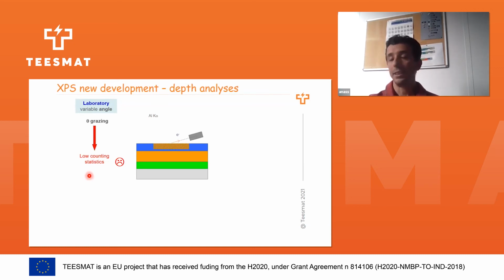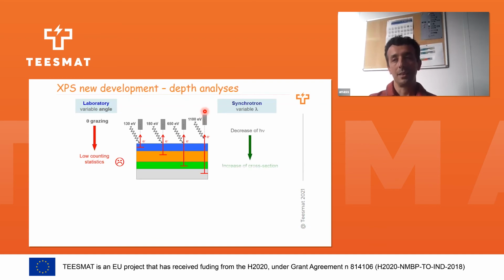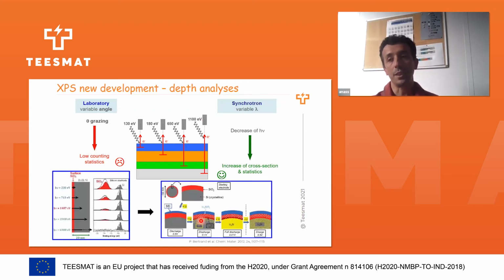There is another way, which is to use different wavelengths. So we can use a photon with 130 eV, 180 eV, for example, and the more we enhance the photon energy, the more we go deeper. For example, that's why I said with XPS nowadays, we can use XPS to understand, for example, the chemical structure on silicon-based battery by changing the photon energy. For example, here, this is a silicon anode with a silicon bulk and a native silicon oxide layer. And by changing the energy, we can probe deeper.